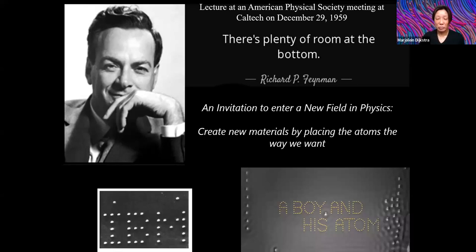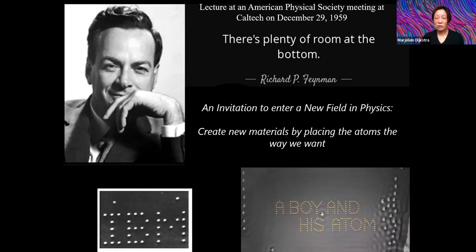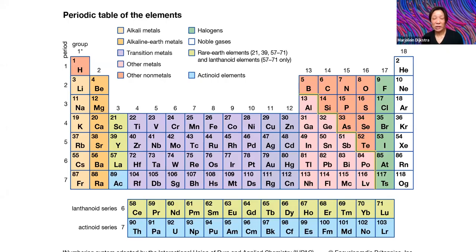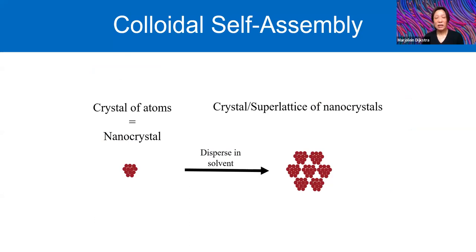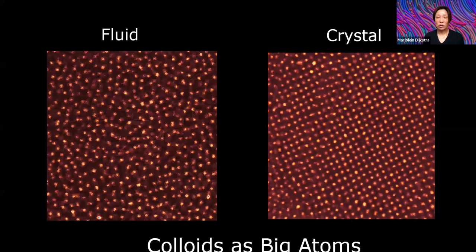And so what would be a much better idea is to start with the periodic table, pick your favorite element or a set of elements, make a compound out of it, and then make a nanoparticle of these selected elements. If you make small crystallites or nanoparticles, you can disperse them in a solvent and then exploit the Brownian motion to use self-assembly and make superlattices or crystalline structures out of these nanocrystals. This is an extremely cheap way to make nanostructured materials.